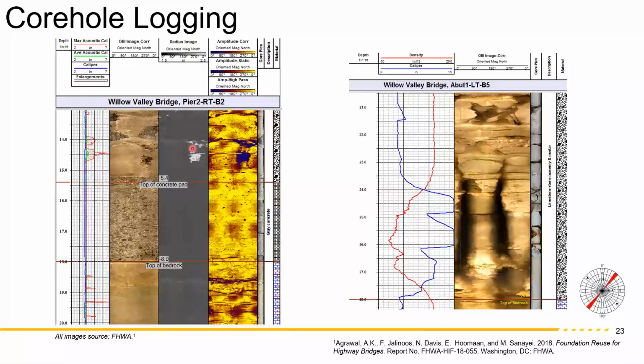So the next slide, the first one, is the optical televiewer. We have the optical camera that you put down the borehole. The tool has a 3-component magnetometer, similar to the magnetometer that Bernie used, to correct for the changes in azimuth as the tool rotates as it goes down the core hole. It also has a 3-component accelerometer to correct for inclination. So what you have is an oriented core. You can look at it in 360 degrees, just open it up like this. So you can see the whole borehole contact information fully oriented. And then you can get the strikes and dips of any feature that you want to take a look at. So that was the concrete pad on the new foundation, and that was the bedrock, and you see the contact was pretty good. Okay, you can also use an acoustic televiewer.